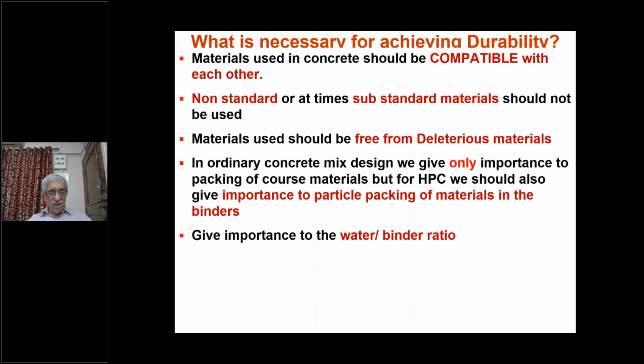We must give importance to the water binder ratio. Earlier, we used to call it the water cement ratio, but because now we are putting binders like slag, fly ash, ultrafine materials, etc., we say water binder ratio is important. Lower the water binder ratio, better will be the concrete quality, as well as it will have good durability.